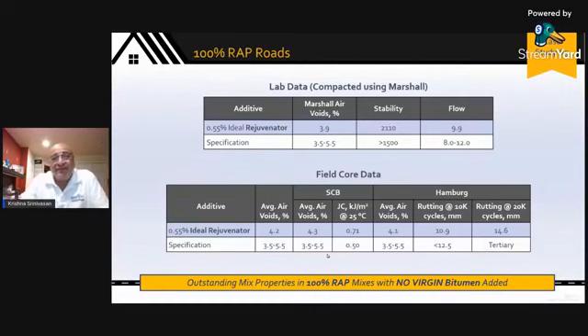Anyway, first we did lab studies. This was compacted using a Marshall to look at the stability and flow numbers, and it met them. And then they put down several miles of roadway. After about 9 to 10, 12 months, we pulled out some cores, looked at the SCB, semicircular beam bending, which is a fracture toughness parameter, and the Hamburg for the rutting. Remember, we walked through this balanced mix design. You're looking to trade off crack resistance versus rutting. We looked at the performance after a year, and we were comfortably exceeding the specification for virgin material.